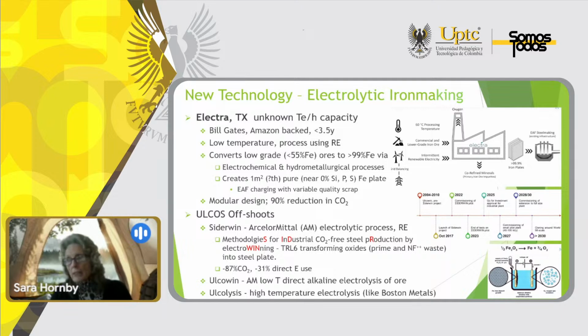It's modular, and they believe that they can reduce the CO2 by 90%. The other low and high temperature processes are off-spins from the ULCOS research that was done back in the 80s and 90s. Siderwin, I've already mentioned, ArcelorMittal. They believe 87% reduction in CO2 is possible with a reduction of 31% in direct energy use.